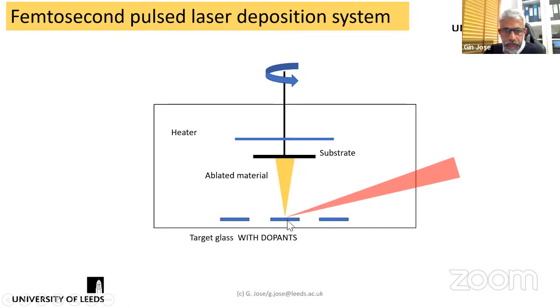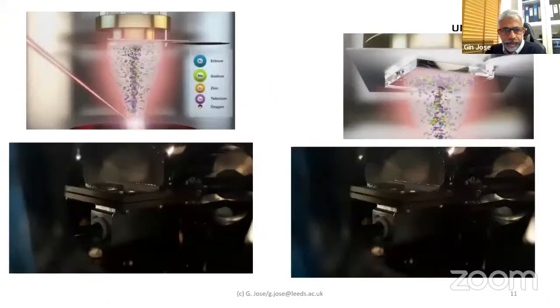So one critical difference between ablation using a UV excimer laser or a femtosecond laser in a dielectric material like glass is that most of the ablated material contains nanoparticles rather than ions. That means the films that you grow using femtosecond lasers can very likely be structurally different from those deposited using, say, an excimer or UV nanosecond laser.